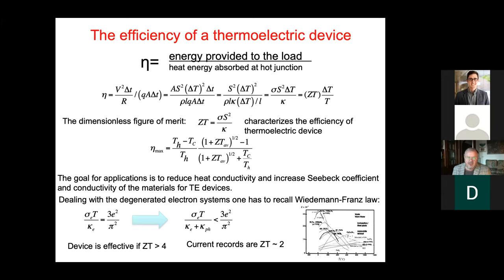So if you make calculations, you will find some fundamental results: the efficiency of a thermoelectric device is the Carnot engine efficiency, T hot minus T cooler divided by T hot, and the expression of ZT. You see that if ZT is small, so I will expand this term, and unfortunately, my efficiency will be very small. So it is not enough to have a large Seebeck coefficient. It is necessary to maximize also